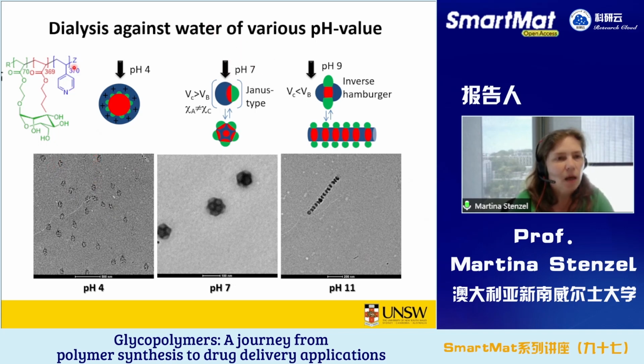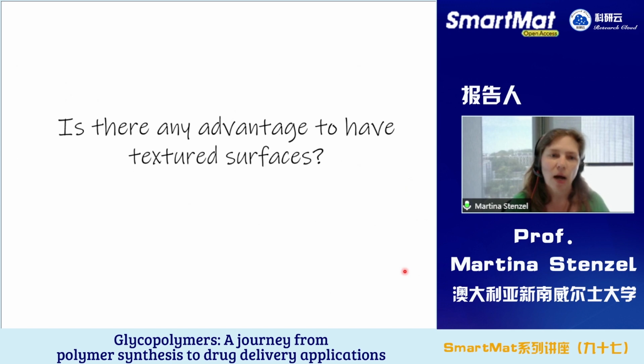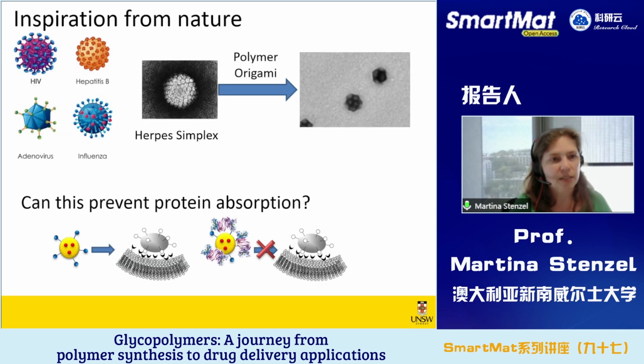However, at pH 7, the blue block and the green block are not miscible with each other. They phase separate, so they form Janus-type particles, which are not stable in water. These Janus particles then form footballs, little soccer balls. These soccer balls have a very scattered surface with little bumps on it. Or you go to pH 9 and you even get these bamboo sticks. So the question was, is there any advantage to having these textured surfaces? Again, look at these virus structures, how they have textured surfaces. What we just did was make nanoparticles that look quite similar to the virus surface.